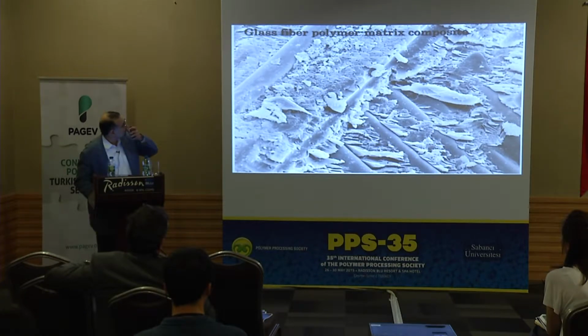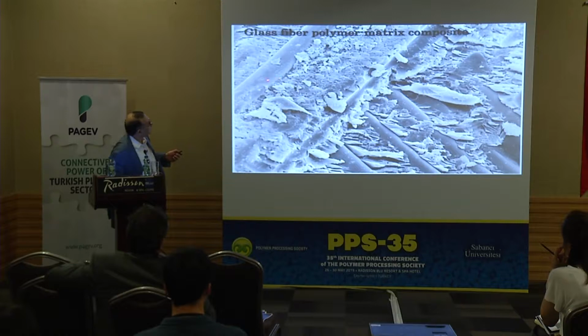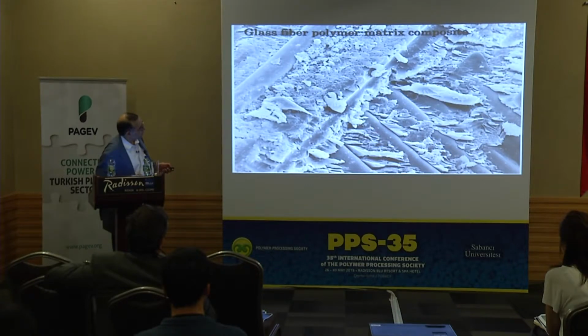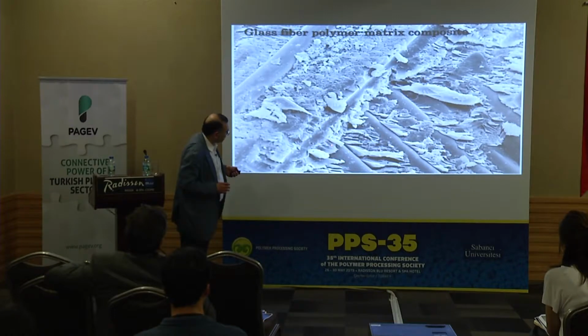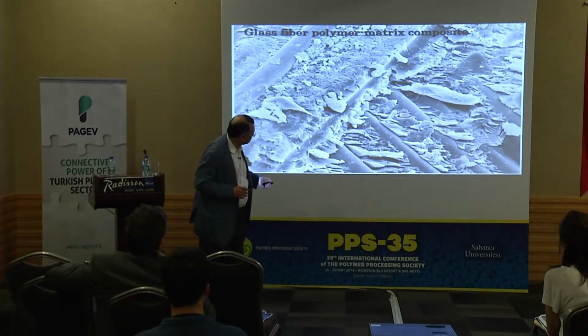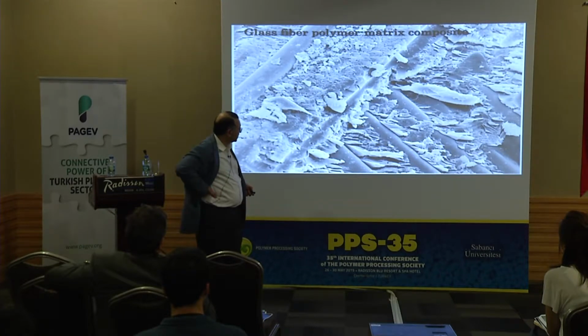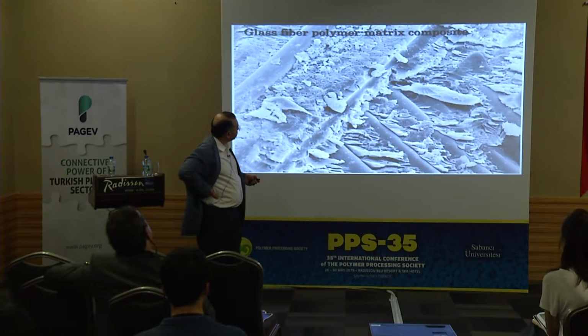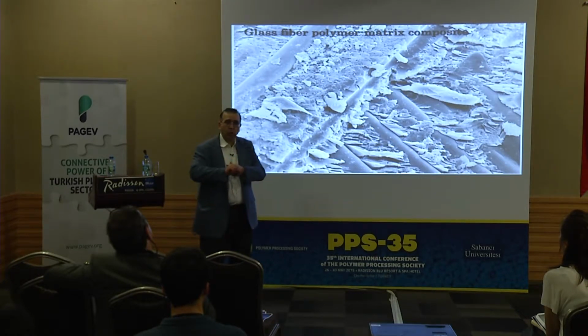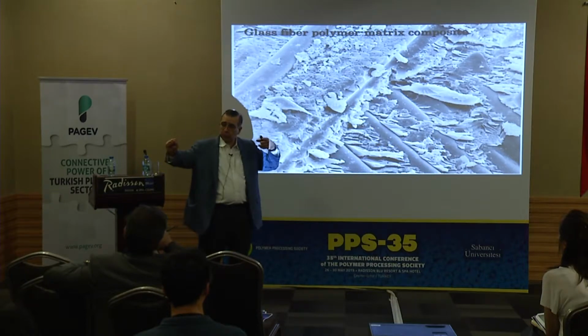This is another fracture surface of glass. I think these are glass epoxy. You see a lot of fracturing. You see fiber surfaces. When you look at the fracture surface, you would like to see a lot of fracture, which indicates that there has been fairly reasonable interfacial properties. You would like to see resin on the surface of the fibers. You really do not want these kinds of clean gaps or the large holes in the resin where the fiber just pulled out cleanly.